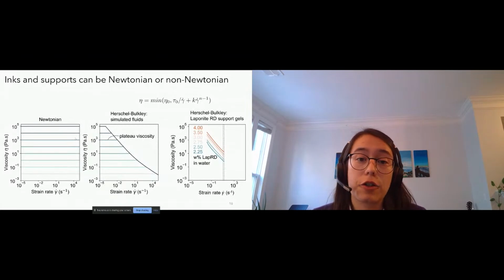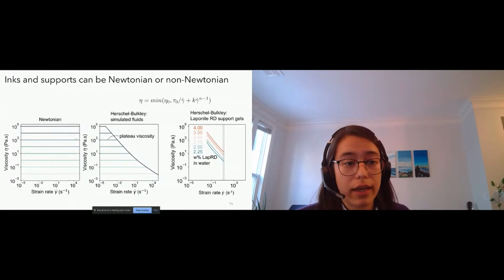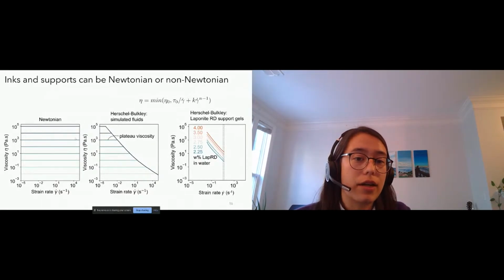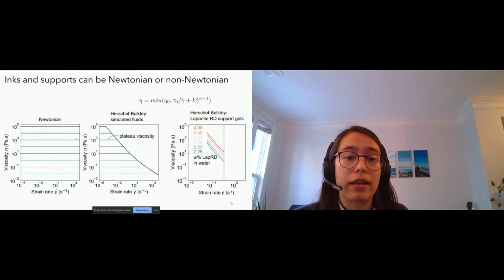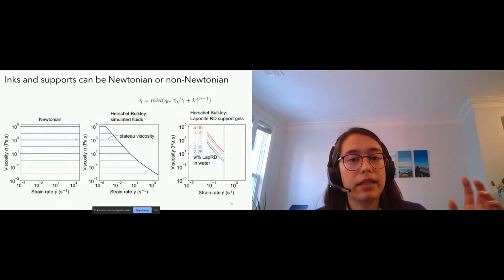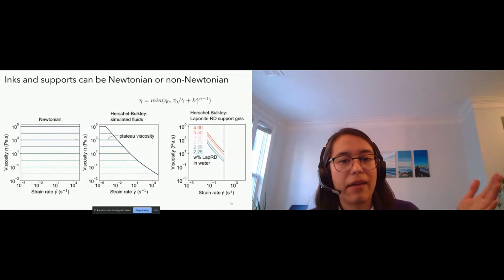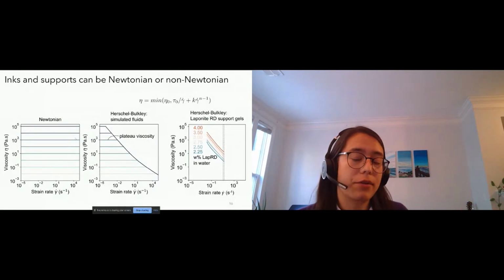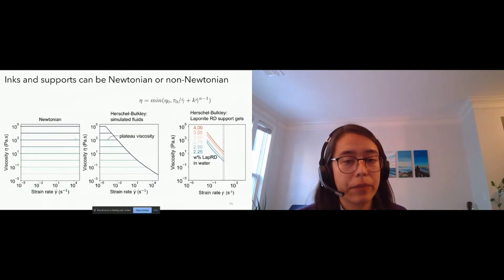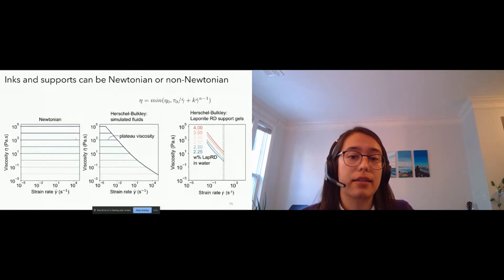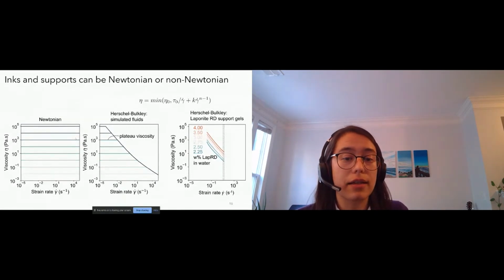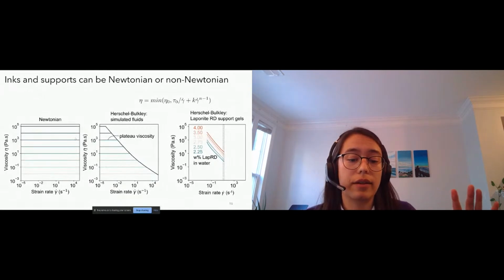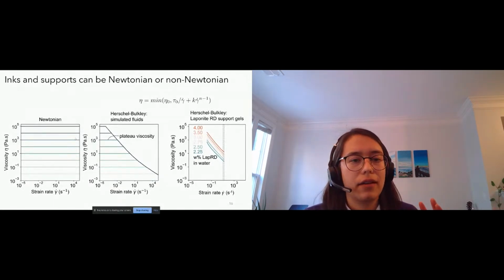We also simulated Herschel-Bulkley fluids. So these are the fluids that I talked about in the beginning, where they're going to behave like a solid up until a yield stress, at which point they're going to behave like a shear thinning liquid. So for these simulated fluids, all of the behavior in the shear thinning region is going to be the same. These are all going to have the same viscosity above yield. But below yield, they have different viscosities, which I call the plateau viscosity. So that is going to extract